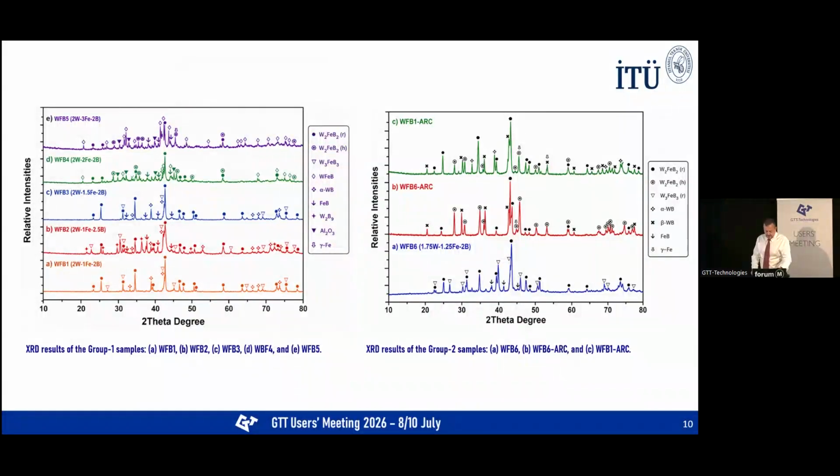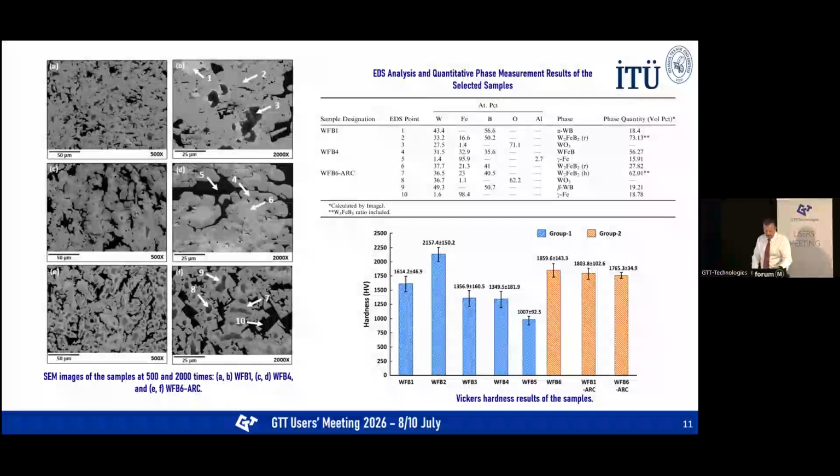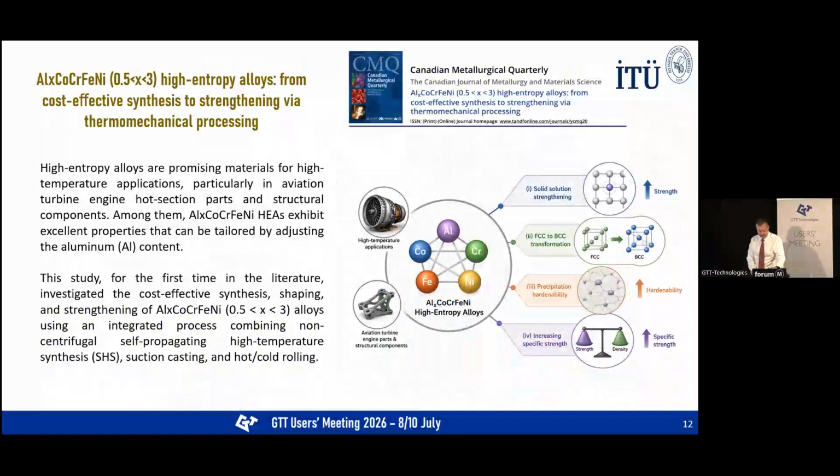So, showing good agreement with the FactSage predictions. Finally, SEM and EDS analysis showed that the experimentally observed microstructures were consistent with the prediction. The hardness measurements also show that such materials are promising for wear resistance applications.